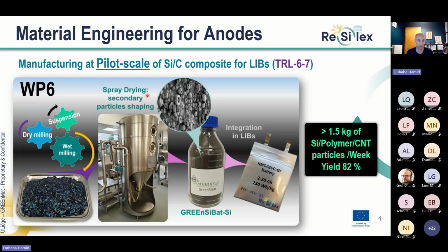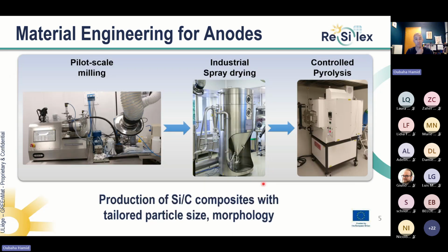So with the RESILEX project funding and support, we at University of Liège are able to take a step further in the silicon composite production, reaching a TRL of 6 to 7 now, and we are able to produce more than 1.5 kilograms per week with a good yield. The proposed approach in RESILEX combines pilot scale milling, an industrial spray drying process, and controlled pyrolysis, and this allowed us to produce silicon carbon composite with tailored particle size and morphology.